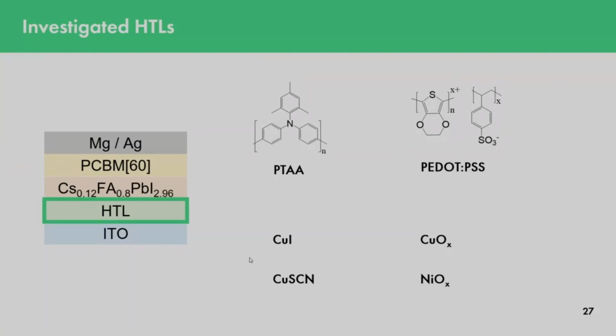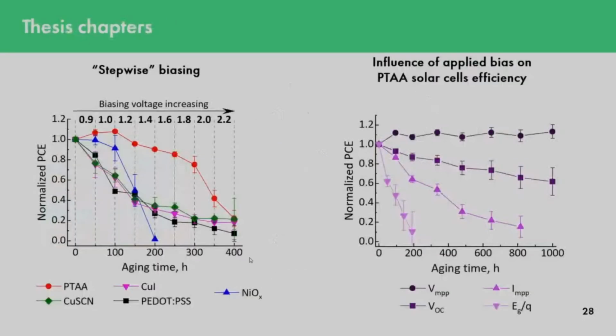I would like to point out that here you can see they are written as copper OX and nickel OX, and this represents that we have some kind of difficult mixture of different oxides. So for example, for copper oxide, we have a mixture of copper 2 plus and copper 1 plus oxide. And for nickel oxide, we have nanoparticles, which are also of very difficult composition, and thus it's established in the literature to write them with the letter X.